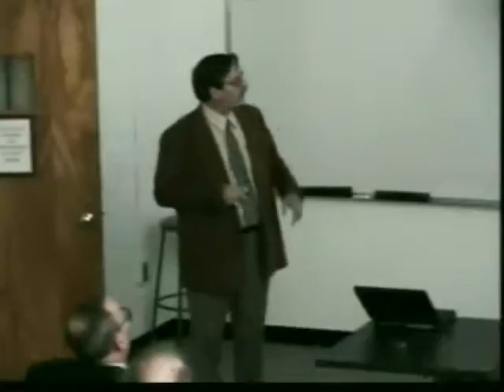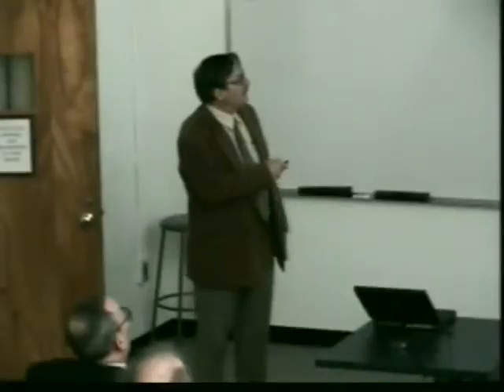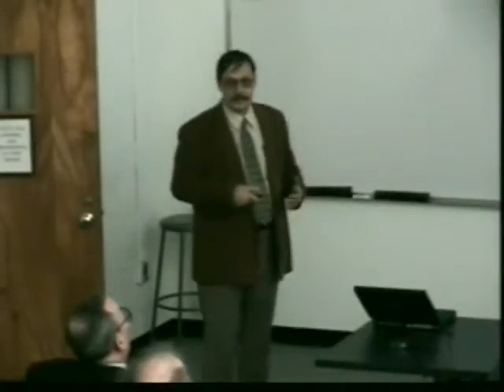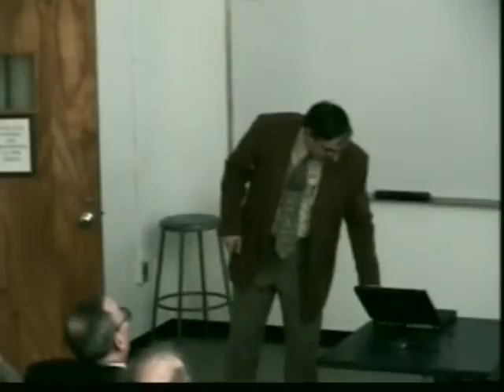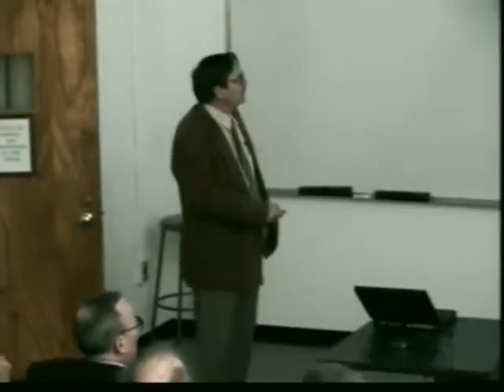An example of the material that we looked at first is a Hanford tank waste simulant from Battelle. This is a borosilicate glass. This is basically the composition of the calcinate. So you take a simulated Hanford tank waste and inject it near the plasma flame, then you inject the borosilicate vitrifying media lower down, and what do you get? Well, these are typical experimental results.